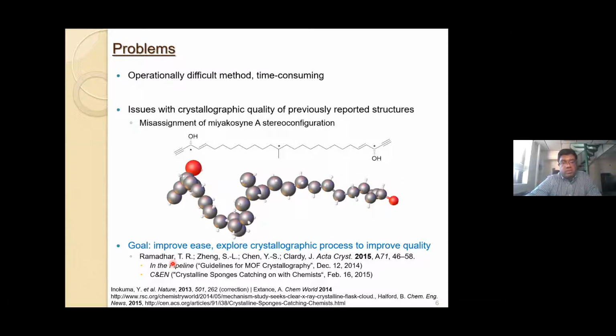And crystallographers also had a lot of issues with the data quality that was reported by the Fujita group, and that all culminated in the misassignment of a natural product called miyakosyne A. They wanted to figure out the stereochemistry of the central methyl group right here, and you have a 50-50 shot, right? It's either going to be R or S, and they got it incorrect. And so they had to publish a correction addendum in Nature, which really dampened enthusiasm for the technique.